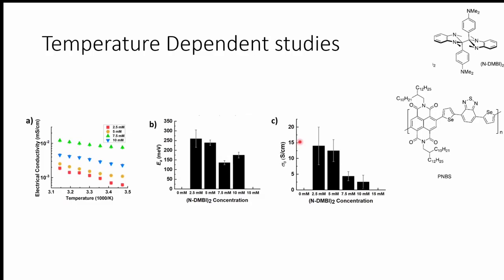And now the other thing is we wanted to investigate how the conductivity changes with temperature. Metals normally have their conductivity suppressed with an increase in temperature. However, here, because this is inverse of temperature, you notice that with the increase in temperature, the conductivity actually increases. Now, from these different doping levels, if you do a fitting using an Arrhenius model, you can extract two parameters. Your EA, which is basically the activation energy barrier for one electron to hop from one side to the other. So imagine you have point A and point B, and your electron needs to hop, and how much energy is the cost for it to hop.